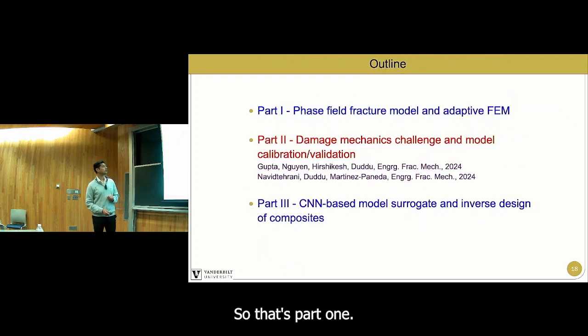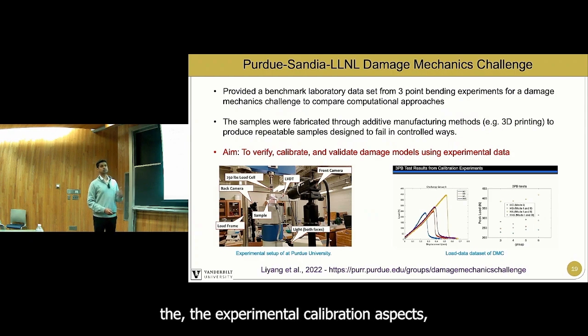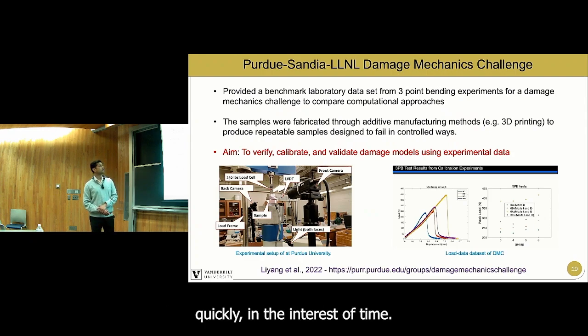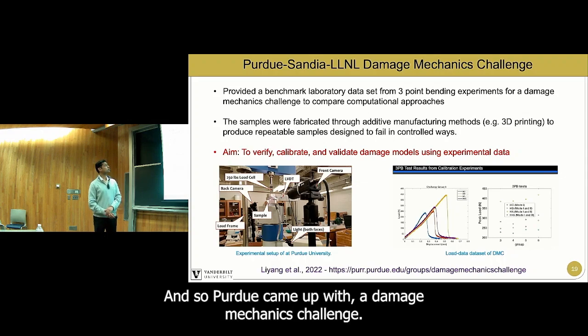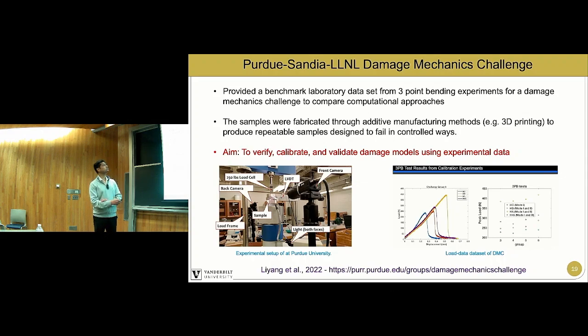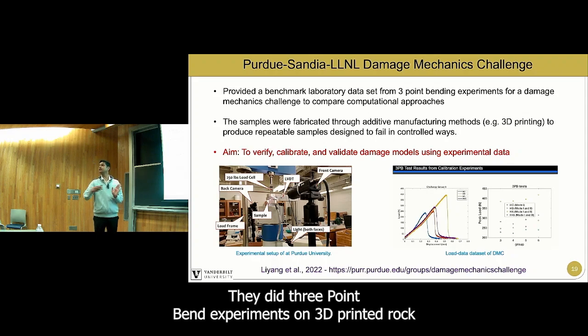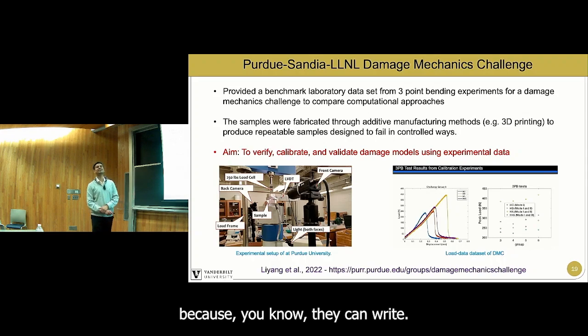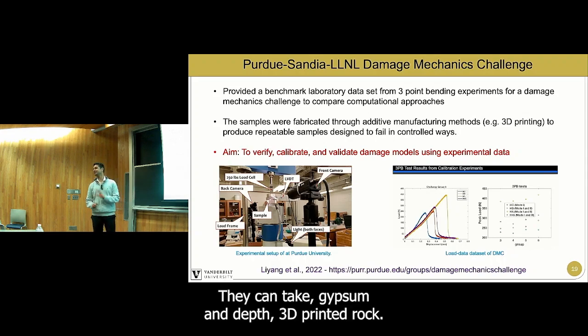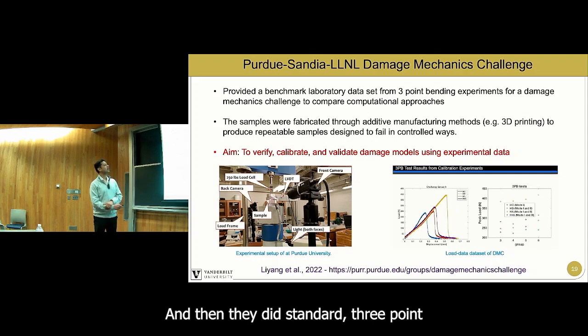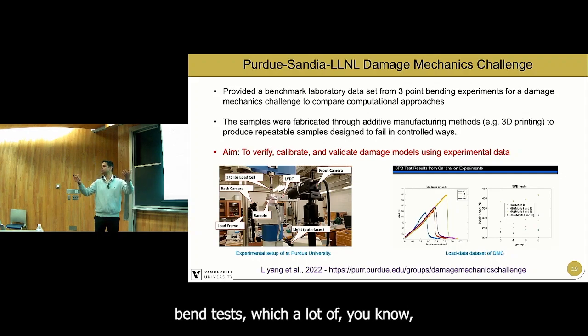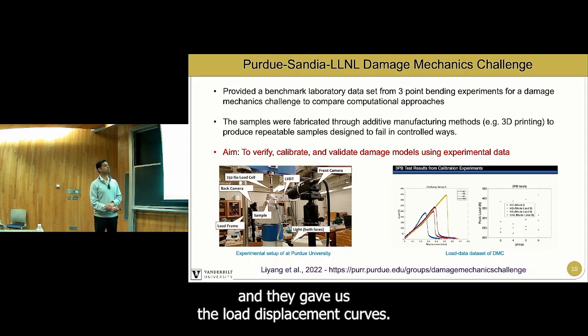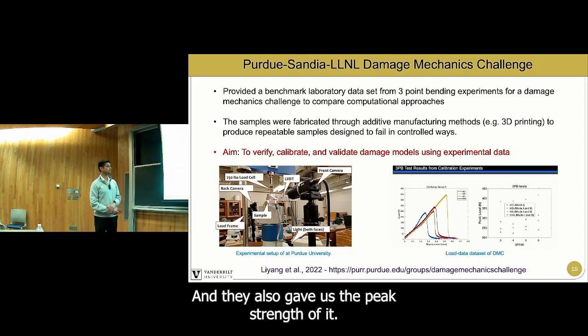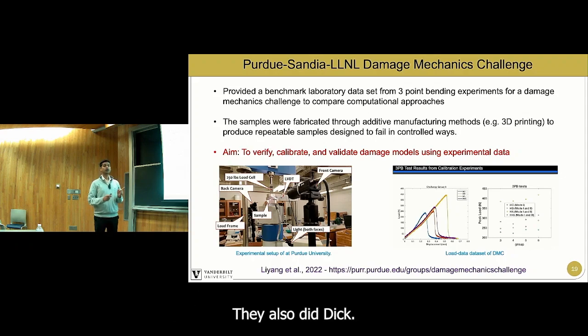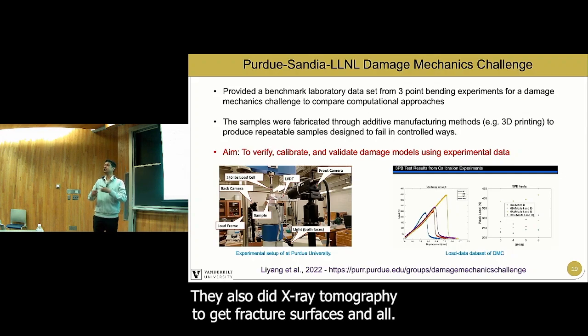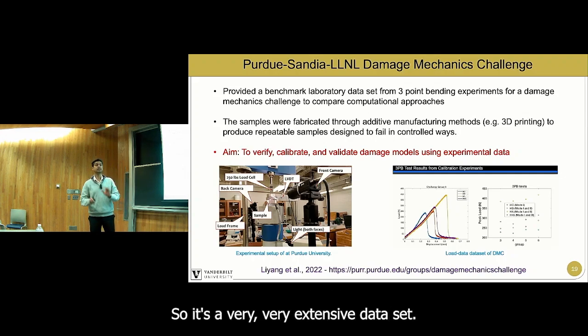So that's part 1. And then I'll try to skip a lot of the experimental calibration aspects quickly in the interest of time. Purdue came up with a damage mechanics challenge. They did 3-point bend experiments on 3D printed rock because they can, right? They have fancy equipment. They can take gypsum and 3D print rock. And then they did standard 3-point bend tests, which a lot of you know. They gave us the load displacement curves, and they also gave us the peak strengths. And the whole data set is given here. They also did DIC. They also did X-ray tomography to get fracture surfaces and all. So it's a very, very extensive data set.